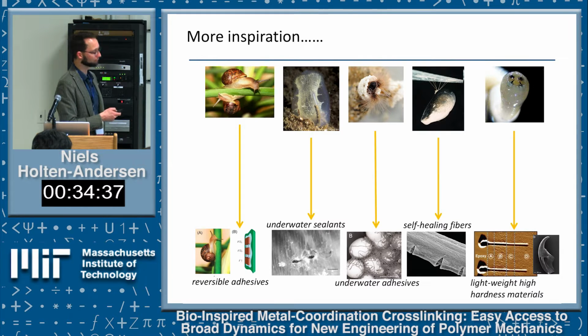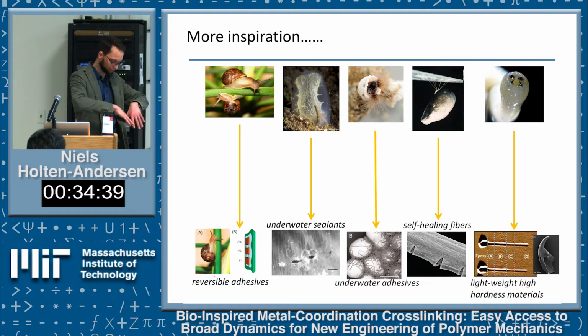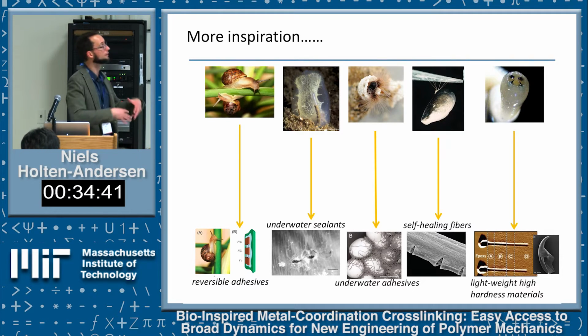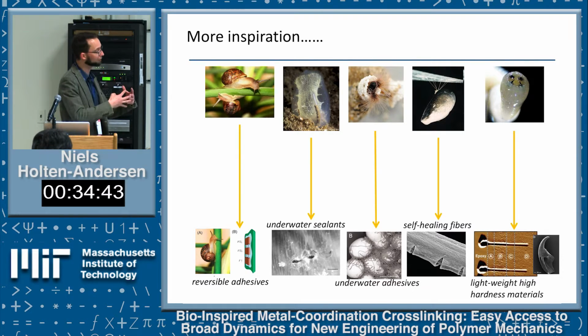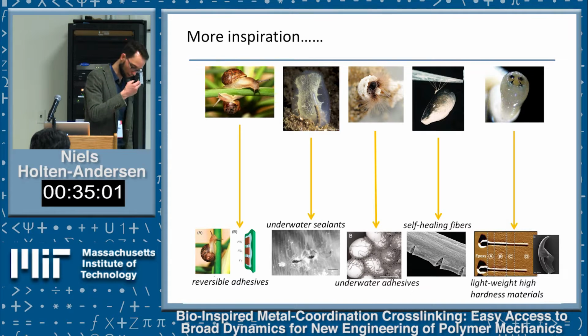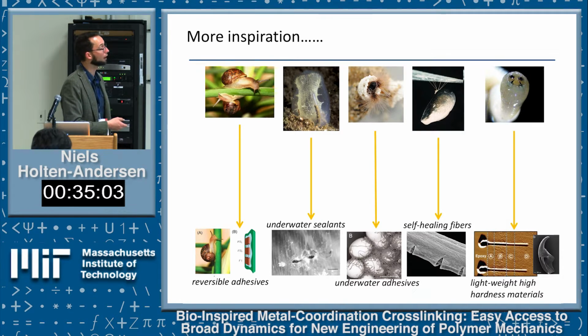They can act as little underwater masons, encapsulating their soft bodies in a tube of sand grains glued together with a soft, sticky glue. This glue has also been found to be very rich in metal coordinate bonds. And again, mussels, as I told you, have these self-healing fibers. But it's not just these soft to semi-soft materials - it goes all the way up to very dense, very stiff, and very hard materials too.